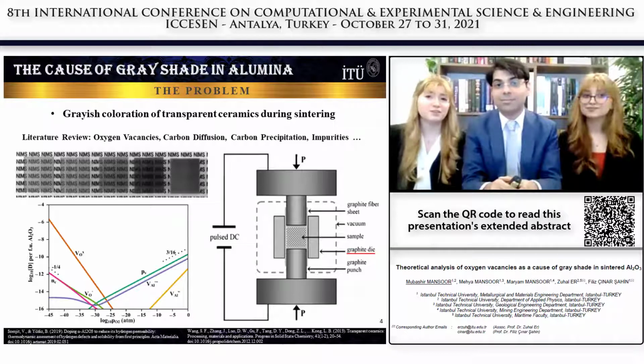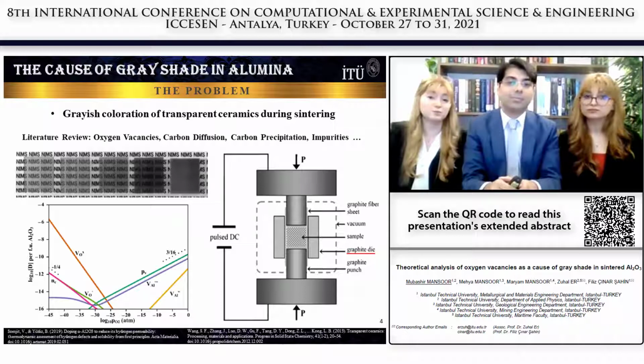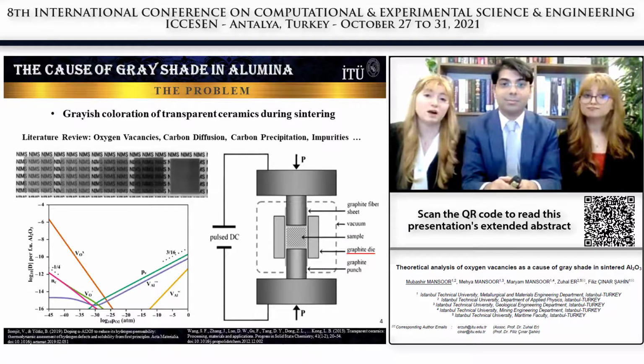Some researchers have attributed this shade to oxygen vacancies because if you look at the SPS equipment where sintering is taking place, there are many graphite components and the atmospheric conditions are inevitably oxygen poor due to the Boudouard reaction. Based on the defect thermodynamics of alumina, oxygen vacancies are a dominant defect under such a reducing atmosphere as seen here. And since subsequent heat treatments of such ceramics under high oxygen partial pressure can make the ceramics colorless, it has led many to consider oxygen vacancy as one of the primary causes of this gray shade.